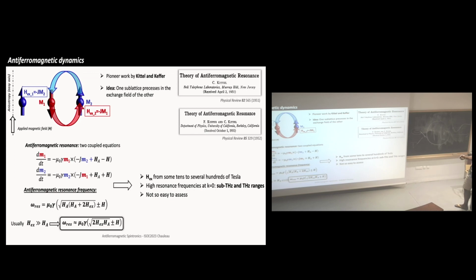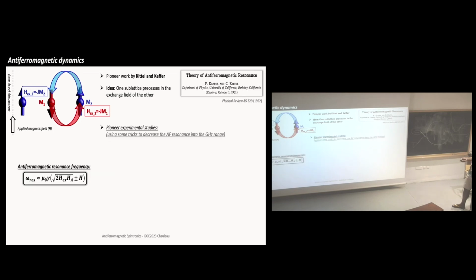So this is really what makes the difference between antiferromagnets and ferromagnets. And the nice thing is that it is at k equal to 0, compared to the spin wave I've just mentioned before. So at k equals 0, we can excite antiferromagnetic resonance directly in the terahertz range. But it's not so easy to access. That was at the beginning of the 50s. The nice thing is that people used tricks to access this resonance, to see the resonance in antiferromagnetic materials.